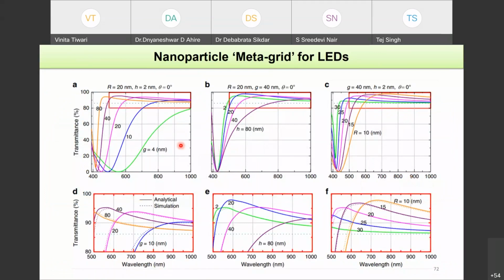For different gap sizes, this dotted line tells you the transmission from a typical LED interface when no nanoparticle is there. And when you form a nanoparticle layer, the nanoparticles are silver nanoparticles of radius 20 nanometer, placed at a height from the interface, with normal incidence. These are different gaps. So when the gap is, say, 20, you see the dotted line, and with nanoparticles you are able to get much higher transmission. And when you zoom in and match it with your analytical, that is, theoretical method and simulation, you can see that they are very close to each other.